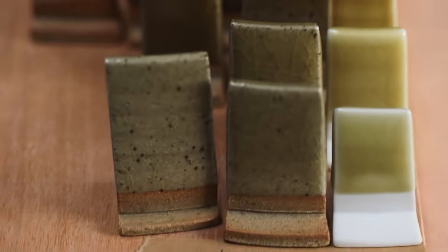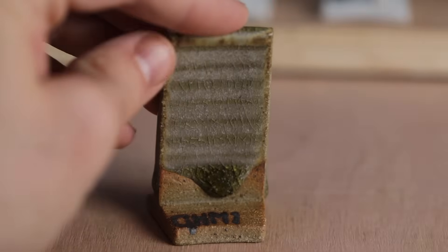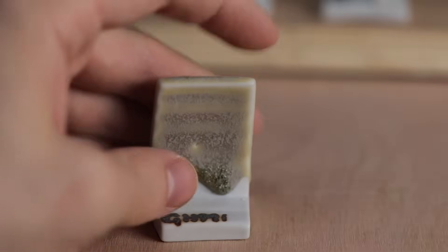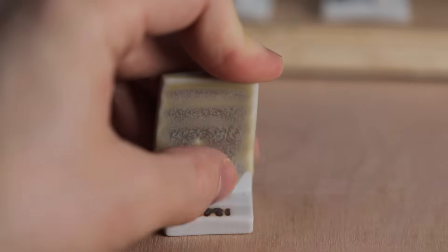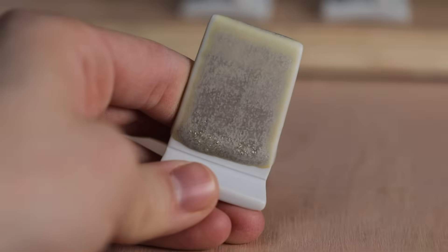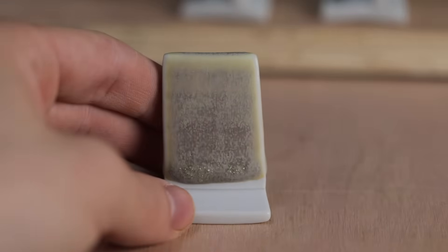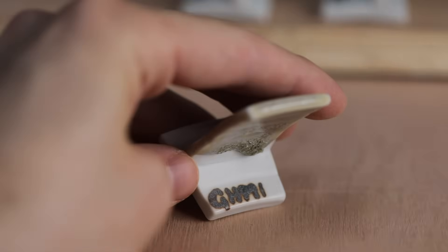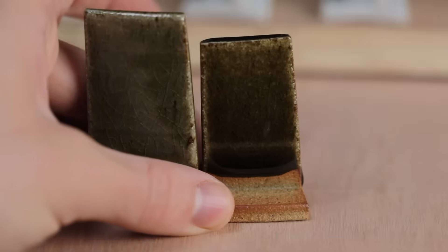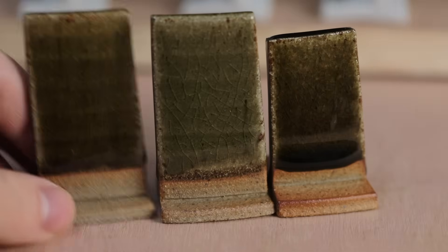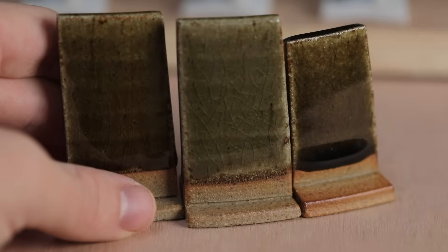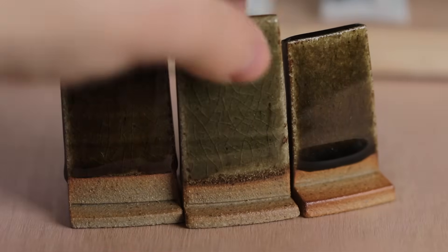The next few are just a few bases, which I tested and really liked, although you may not use. This is the classic Greenwich house matte base, but with 1% red iron oxide and titanium dioxide, again to try and get something that resembles a yellow. But instead I ended up with this, which has quite an amazing texture and surface. But where it pools, it boils and creates these little sharp bubbles. These next three are based from an amber celadon by Alfred's Grinding Room on Glazy, who not only has the most beautiful tiles, but an incredible collection of glazes too. I altered the clay content considerably and essentially tested different colourants from left to right.